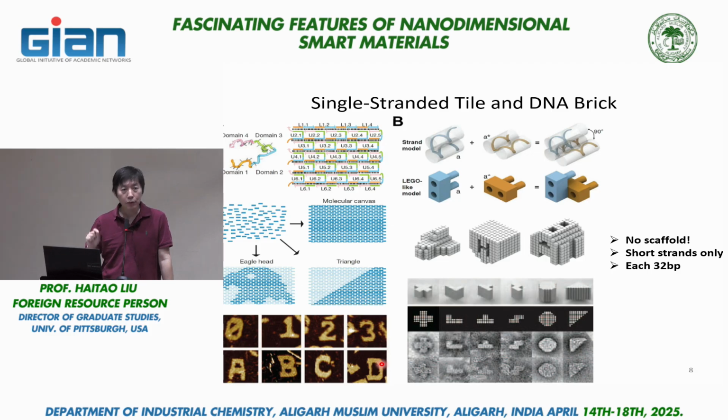What's beautiful in this construction is that you can use the same batch of DNA sequences to produce any shape you want within that size limitation. You no longer have to design another 300 sequences every time you want a new shape. All the shapes here, for example, are produced by the same batch of DNA sequences. The only difference is which ones you eliminate and which ones you keep in the annealing.